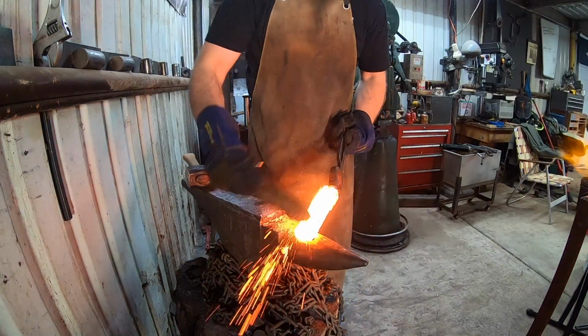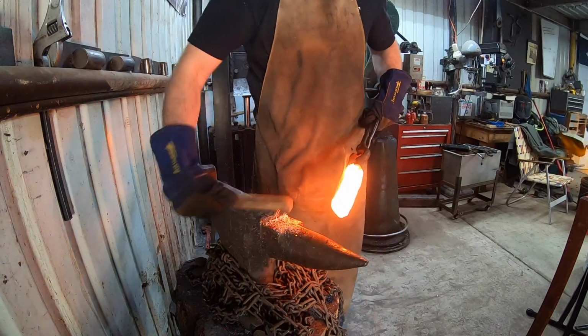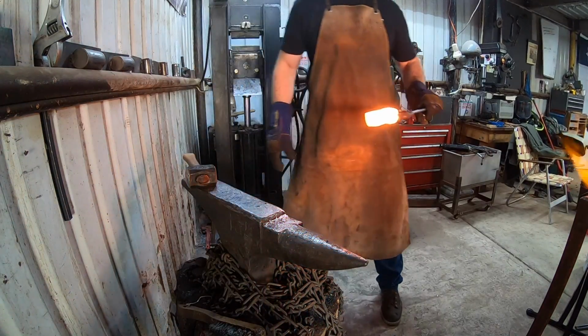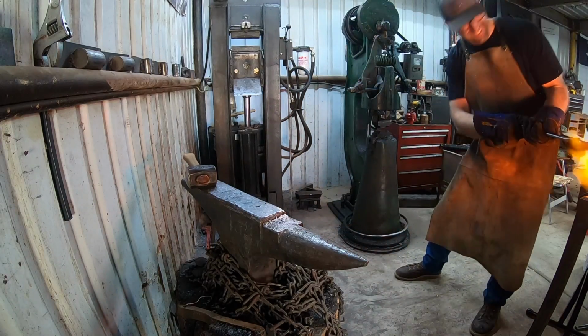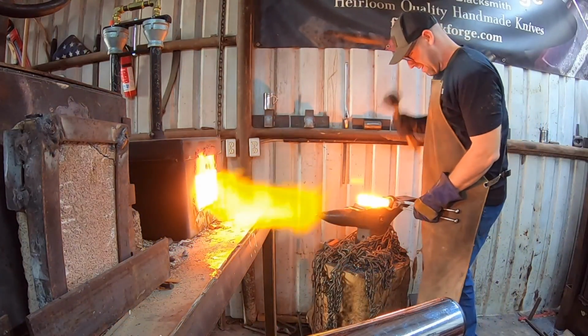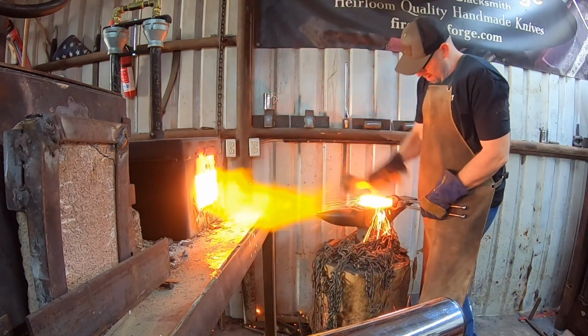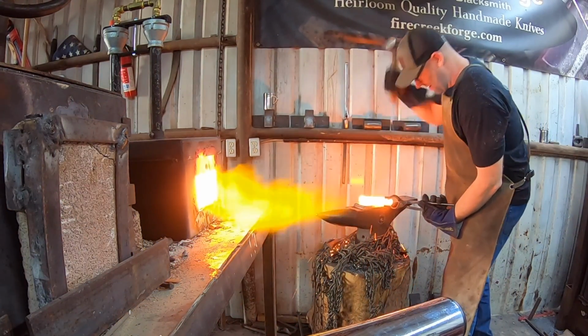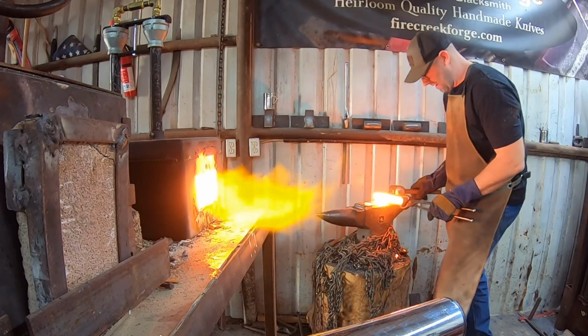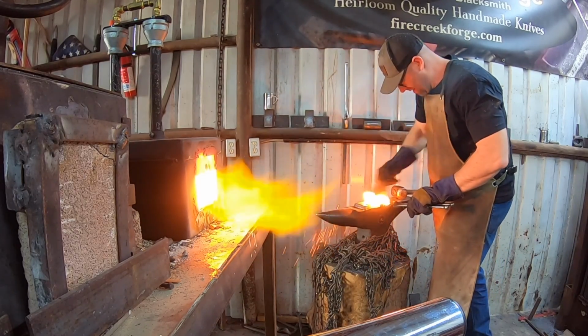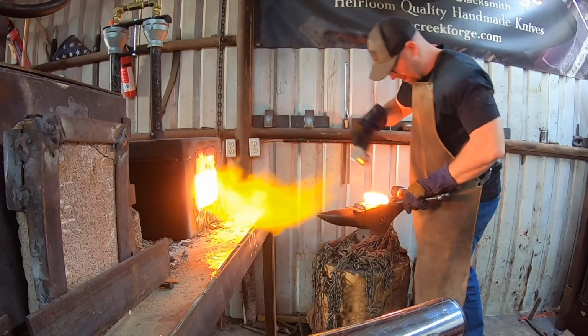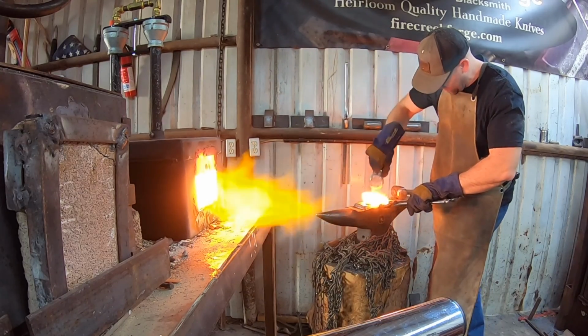52-100 and also steels like 51-60 don't really like to forge weld to each other very well, to the same steel, because of that chromium content. That sort of makes it more difficult to forge weld together. That's what we have here. We have 3 pieces of 52-100 that we're trying to forge weld together, but with the appropriate heat and protection from atmosphere, technically you can forge weld almost anything.